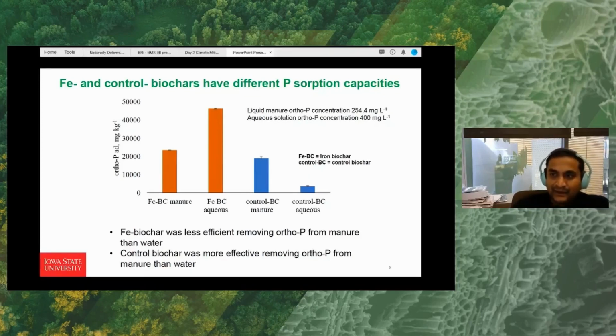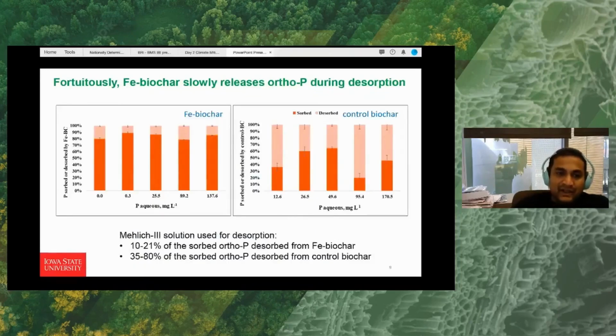Next slide, please. When we did the desorption study, the iron biochar slowly released ortho-P. On the left-hand side, you can see the iron biochar, and the right-hand side is the control biochar. The dark red is the absorbed amount, and the light red color is the desorbed amount. You can see that the iron biochar holds more phosphorus and releases less phosphorus during the desorption study, whereas the control biochar released more phosphorus during the desorption study.